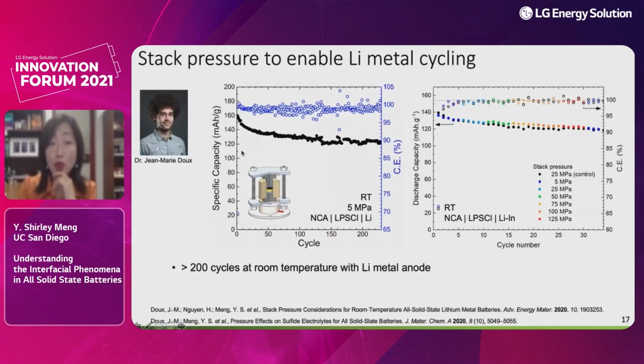So I want to show you the stack pressure effect on lithium metal cycling. We can cycle very well with 5 megapascals for the NCA versus lithium metal at room temperature. Again, I stress the current density is low, but you do see the degradation, which I will mention later—it's really a complex effect due to the mechanical response of the solid state batteries to the stack pressure.